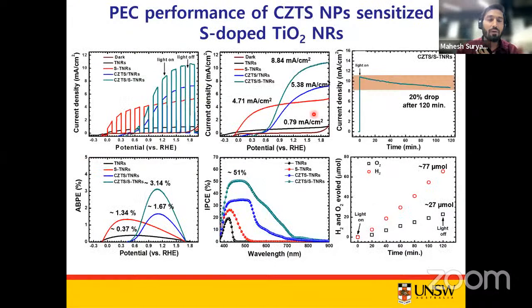Before that, I will briefly explain how we prepared these TiO2 nanorods. We prepared the TiO2 nanorod arrays using a well-established hydrothermal method, using deionized water, hydrochloric acid and titanium butoxide, carrying out the reaction at around 150 degrees centigrade for 9 hours, followed by annealing at around 450 degrees centigrade for 30 minutes. As explained earlier, the performance is comparatively lower. Then we tried loading the CZTS nanocrystals and also doping sulfur into these TiO2 lattices.